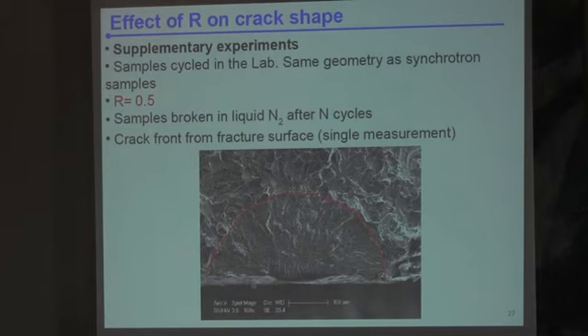because at that time we started discussing the effect of crack closure. Unfortunately, we couldn't go back to the synchrotron and do more experiments at different load levels, stress ratios. So what he did, he tried to do one experiment in the lab, cycling the sample at a different load ratio, and then just breaking them open after the crack had propagated. So of course that gives you only 1 point. That's very poor data, but eventually that gave some very interesting results.